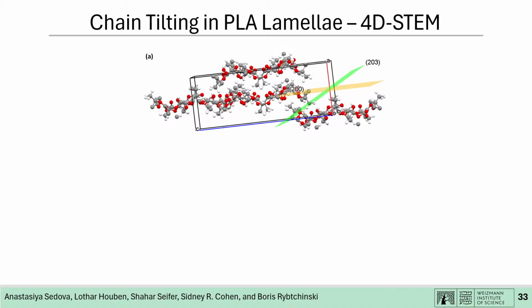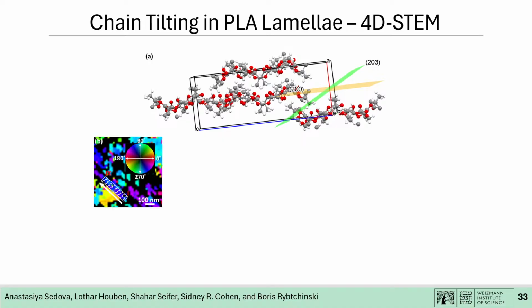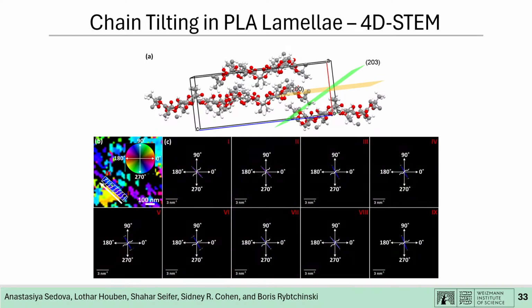So what we can do with these properties and the technique, we can isolate a lamella, go along the lamella, extract a diffraction pattern at each point of the lamella, and by simple analysis, by connecting two equivalent diffraction spots, we can identify the orientation of the lamellar chains. Basically, when the polymer crystal is formed, the chains are folding, and we can see how those folds are oriented compared to the lamellar normal. Until recently, it was believed it's just perpendicular, but one study before us on another system showed that it's not true, and we could show it here as well.